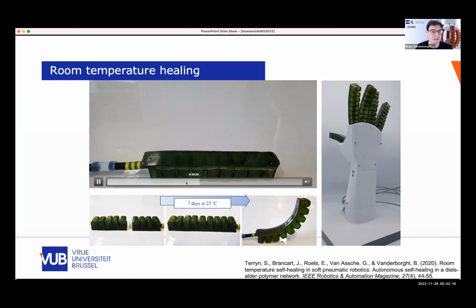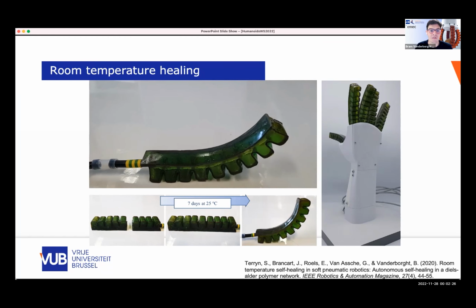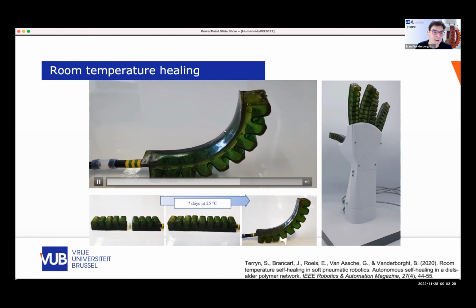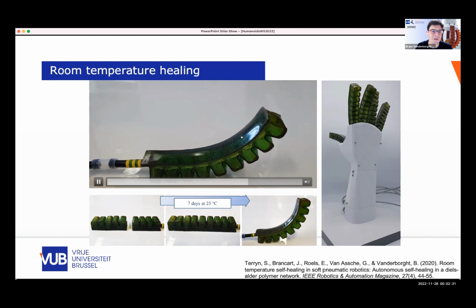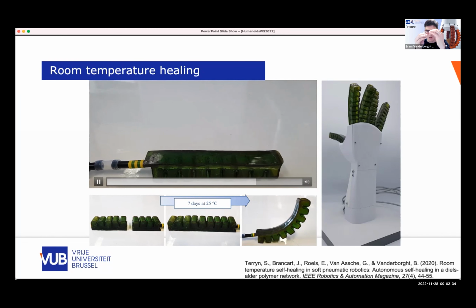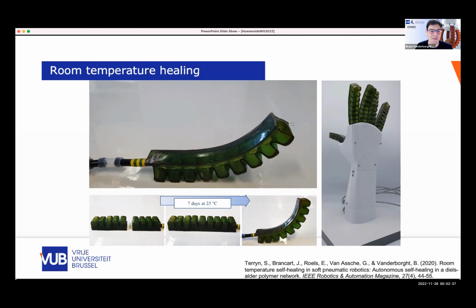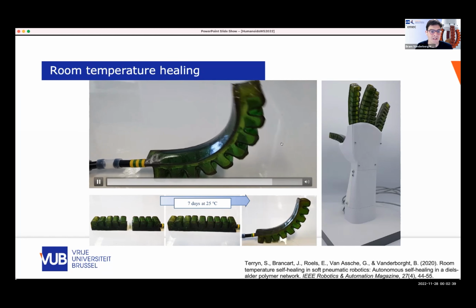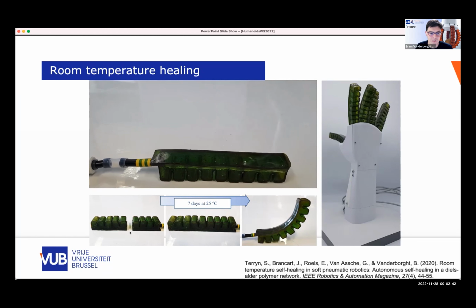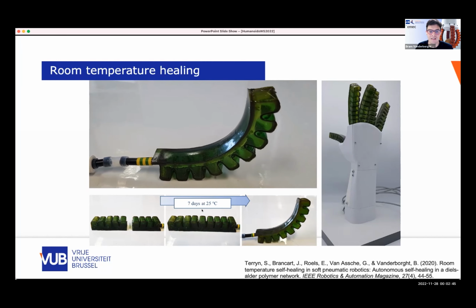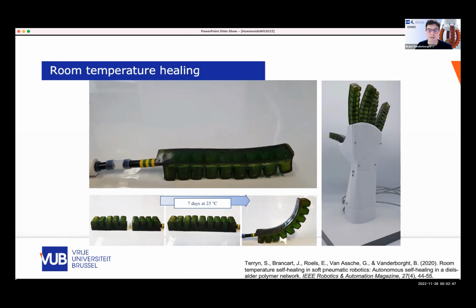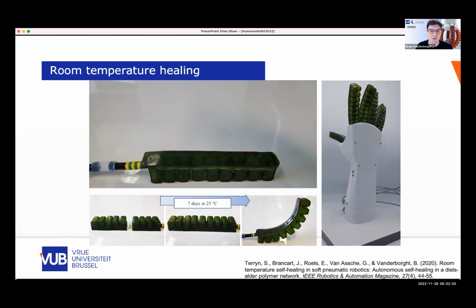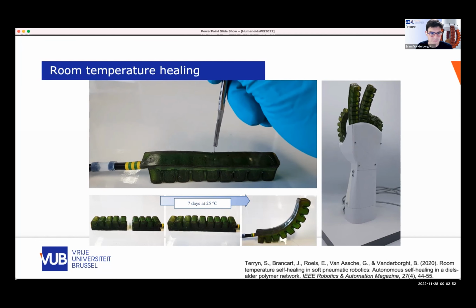And here you see that we damaged the material, and you see the damage being healed. Because at the inside of the finger, the healing is fast enough, and you see we damaged it a lot, and you see scars completely over the finger due to not completely proper alignment, but it's enough to restart working. If you completely cut the finger in two, we need here 7 days at room temperature to heal, but in the meantime, we were already able to bring this number down.